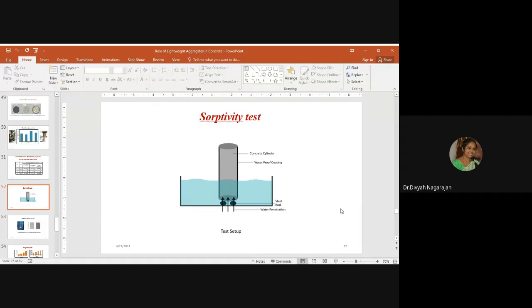Sorptivity test. The durability test plays an important role in lightweight aggregate concretes because of its surface structure, porosity, or its nature. So I have carried out the sorptivity test in order to evaluate the penetration of water against the capillary index. A concrete cylinder was used for this purpose, and it was provided with two layers of waterproof coating. A tub was filled with water to about 2 centimeters, and in order to allow free penetration of water, steel rods were kept at the bottom. The sorptivity was observed for 24 hours.